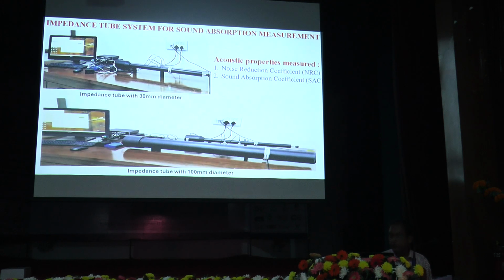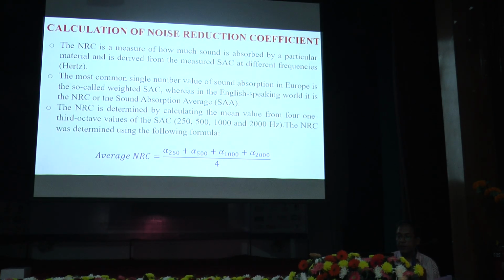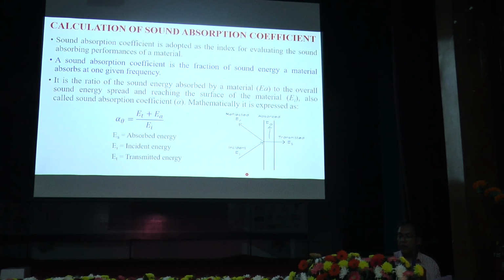Then this is the actual impedance diagram, the impedance tube, and we have the calculation of the noise reduction coefficient. For the noise reduction coefficient, we take the average of the sound absorption coefficient at different frequencies, and we have the calculation of the sound absorption coefficient.